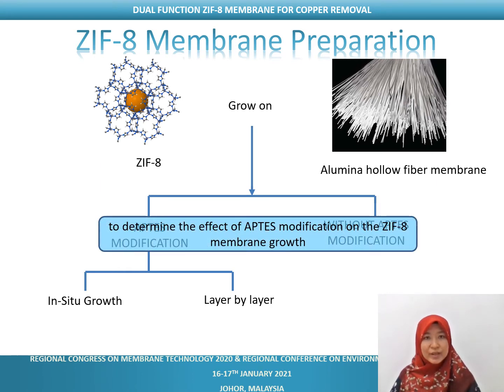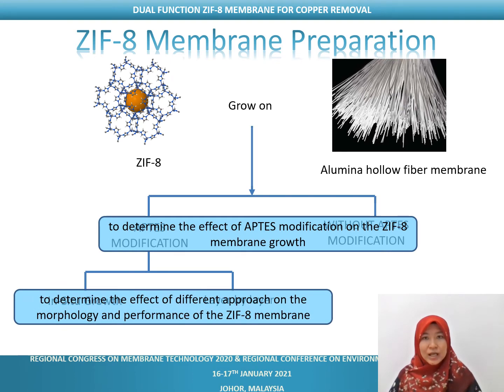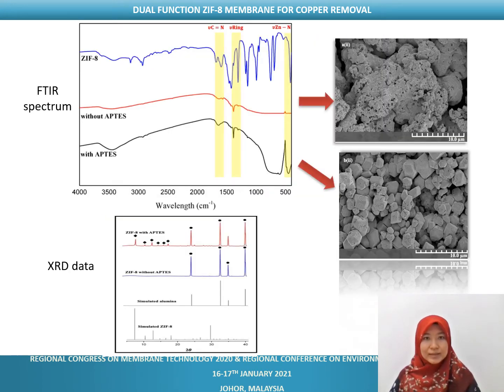Then, the ZIF-8 membrane on modified alumina were grown using two different approaches, which are the in situ growth and layer by layer techniques. This is to determine the effects of different preparation approach on the morphology and performance of the ZIF-8 membrane. The chemical characterizations and morphology of the prepared membrane were determined using FTIR, XRD, and FESEM.